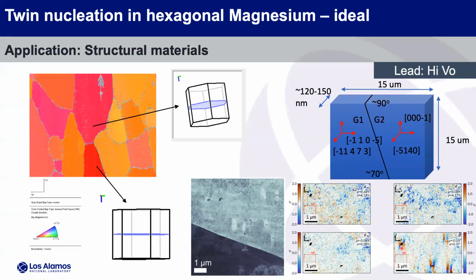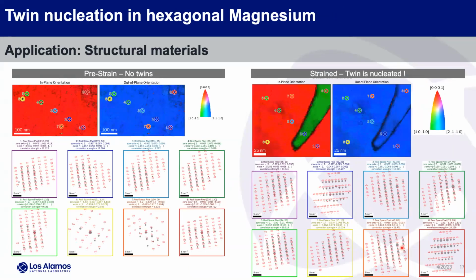Take this and strain it in situ in a TEM, and what you get is a twin forming. So this twin formed. It's the only experiment that we got to work, so this is what we went with. We don't have any reproductions of this just because the experiment is so hard. But we got the twin to nucleate, and we got the twin to stop. It nucleated and stopped about 50 nanometers from the grain boundary.